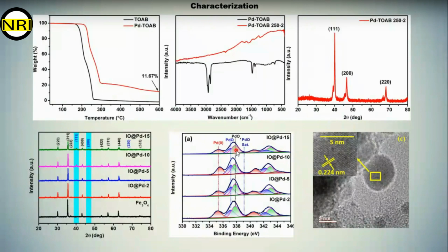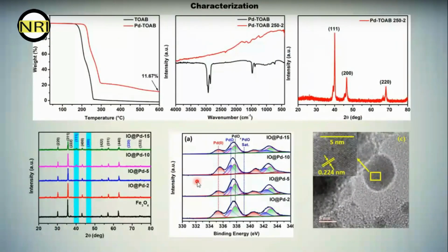So how are we getting this palladium oxide in the sample? Because we are heating the sample at 250 degrees C in air. In air, oxygen is there, and the surface of the palladium captures oxygen from the atmosphere, and that is why palladium oxide forms. But this is not the entire structure of palladium. It is not fully palladium oxide. It is just a surface oxidation of palladium, because we could not see any palladium oxide peak in the XRD. So it is just palladium at the core, and the surface of the palladium core is palladium oxide.